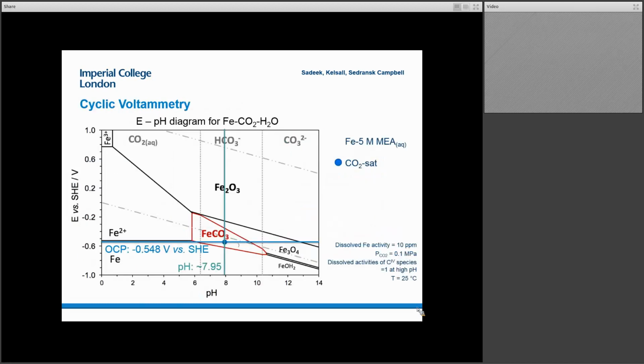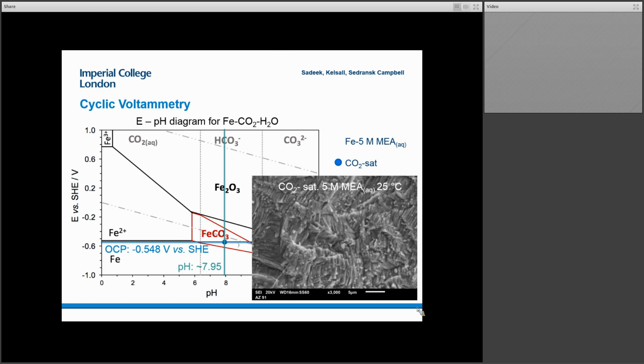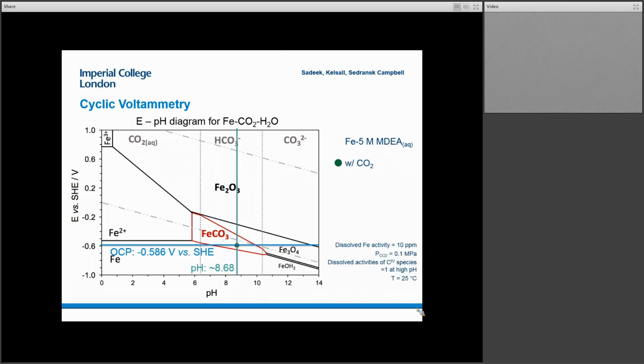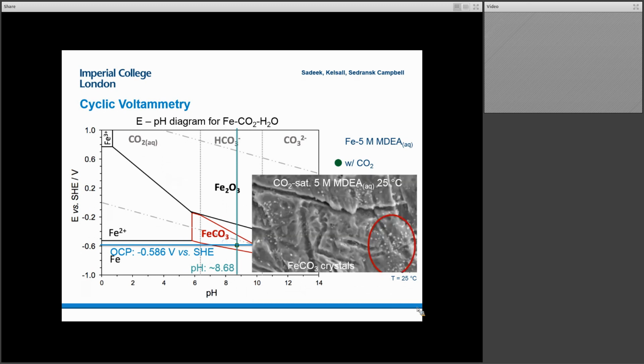Okay, so where does this land us? So one of the things we wanted to look at first was how open circuit potential was different between those two amines when they have CO2 saturation, to try to understand perhaps that's part of the driving force. But in fact, we see that MEA with a pH of approximately 8 when it's fully loaded with CO2 lands firmly in what we would thermodynamically predict as the iron carbonate region. And we don't see any iron carbonate. But by contrast, when we do the same thing with MDEA, which has a slightly higher pH, we do see the formation of these crystals.